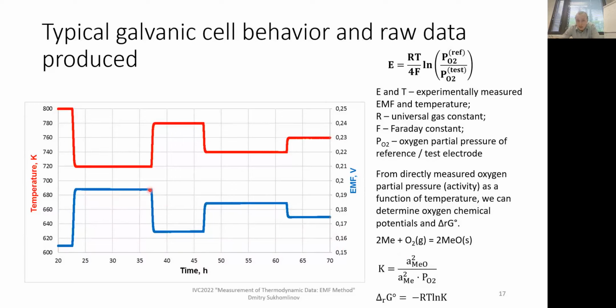Once we realize that EMF doesn't change with time anymore, we accept it as a data point. And then we usually calculate an average over a few hundred data points, so maybe a half-hour time frame. And then we can switch the furnace temperature by increasing or decreasing, doesn't matter. And then we measure a new equilibrium at another temperature. And that's how we collect plenty of data points, and that's how we measure delta G of that reaction as a function of temperature.